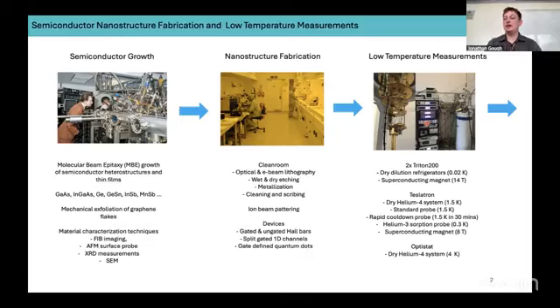within our cryostat systems. We have two dilution refrigerators, which have a base temperature of around 20 millikelvin, depending on noise levels. They also come with a 14 Tesla magnet, and we have two dry helium-4 systems with a base temperature of 4 Kelvin and 1.5 Kelvin. We typically characterize our samples on these higher temperature systems and then cool them down to lower temperatures.